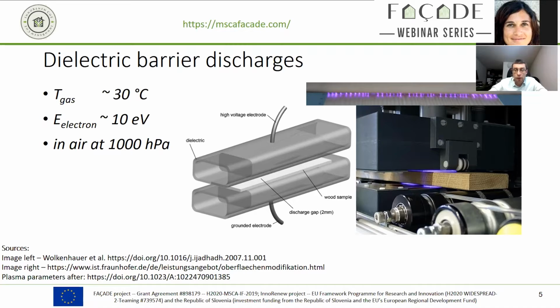One particular feature of these kinds of plasmas you can see in the top image, which is that the plasma treatment affects the early wood and the late wood, if we're speaking about wooden materials, in different ways. This is brought about mainly by the different conductivity and the different dielectric parameters of these parts of the wood. But it's also something that's quite typical for other materials. So if I have a heterogeneous material with different regions, it might well be that the plasma treatment affects different regions in different ways. So for this particular plasma, that's something just to keep in mind, because it's not the case for all plasmas, but for this kind of setup it is.